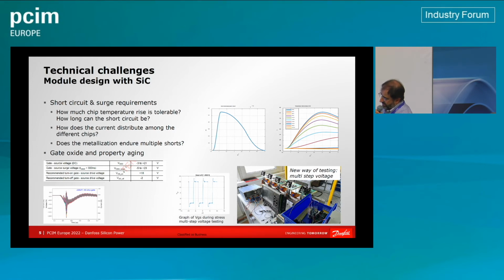And what you can see is that during the turn on event of the other side, you see some spikes and some transients there, which can actually go all the way down, say, to -10, -12 volts. Those are short-term transients, about 50 nanoseconds or things of this type, but certainly they exceed the typical recommended operation values of the chip suppliers. So one of the things that you have to make sure is that that will not cause long-term degradation on the modules. And for example, what we have been doing in order to make sure of that, and not to rely simply on chip manufacturers' statements, is we build our own stress testers.